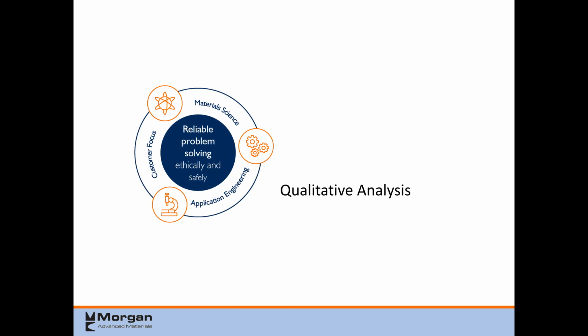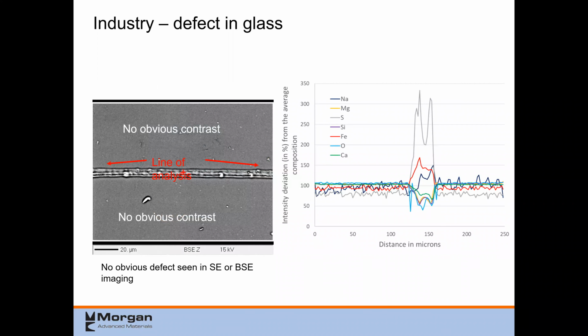Some examples of qualitative analysis that you can do in the microprobe. This was a very big company that everyone knows that produces glass. And they could hold the glass up to the light and see that there was like a shimmer of some sort of defect in there. And they wanted to know what it was. Well, when you look at imaging, you don't see a contrast between where the defect was and the glass itself. So it was very hard to locate.